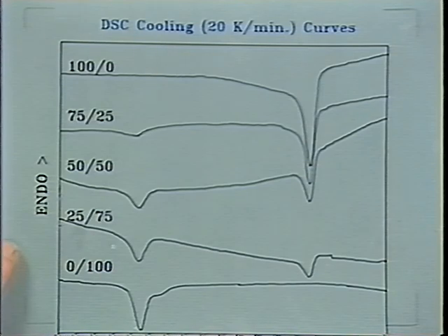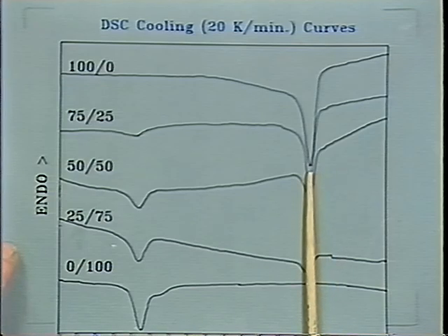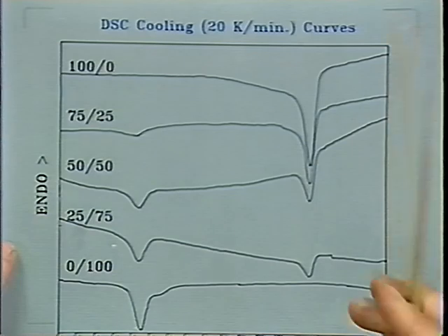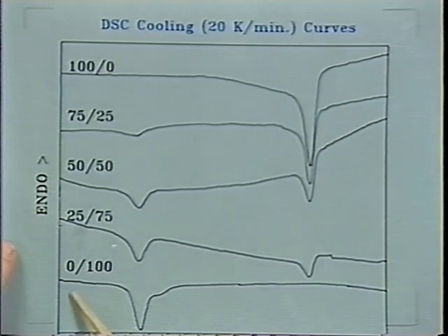So those are cooling curves. I would assume that this is the cooling behavior of the Vectra material at cooling of 20 Kelvin. We know that it will solidify at about 255, and this will be the cooling transition of the Tennessee Eastman material. So this is the curve all Vectra, and this is the curve all Tennessee Eastman.